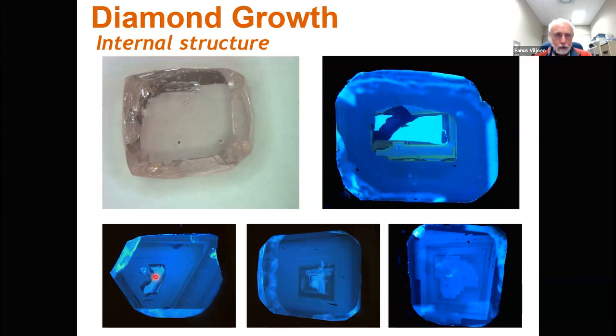In this case, we have a core to the diamond. That's probably the initial seed on which the rest of the diamond grew, probably through a series of volatile pulses. You can see the same kind of process over here. Note the pulsed type of growth of this diamond, and the same type of thing here. So essentially what this means is that diamonds tend to grow like an onion would grow. It starts off with a core, and then if you have a variety of growth events, which might be related to intermittent fluid flow through the lithosphere, you get progressive diamond growth.